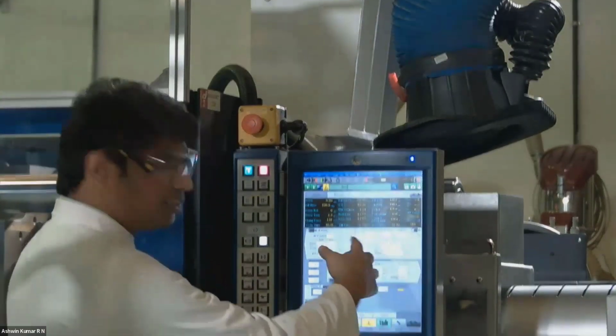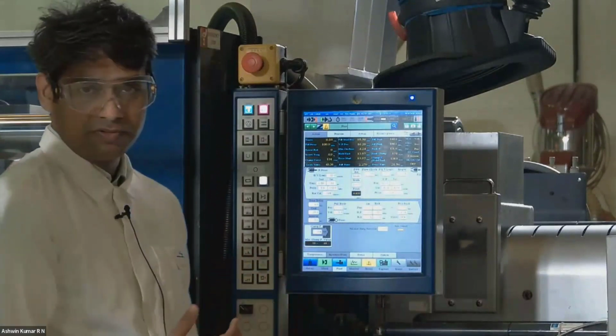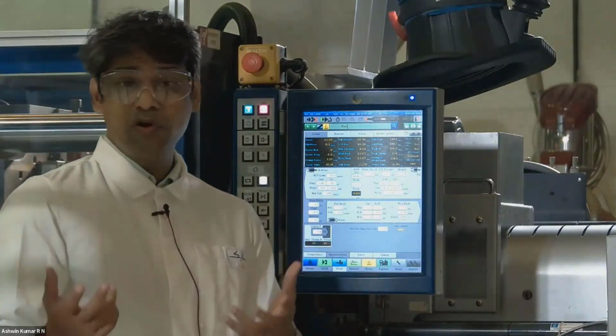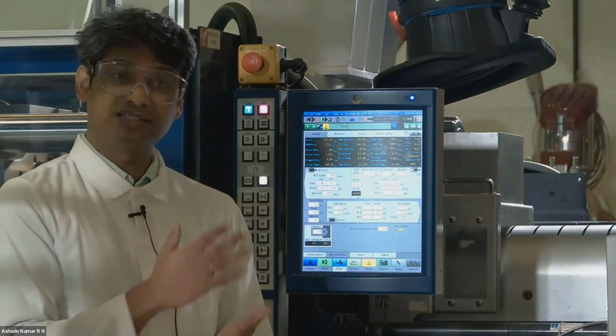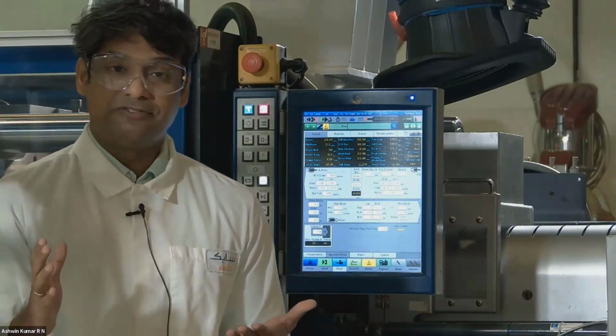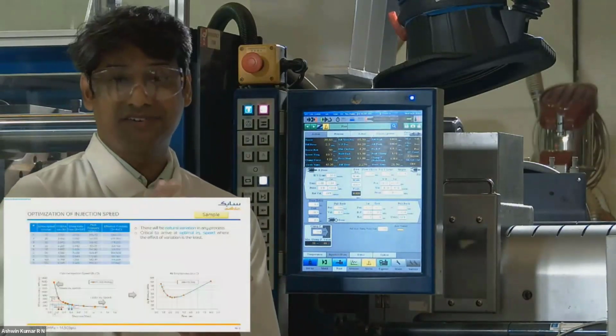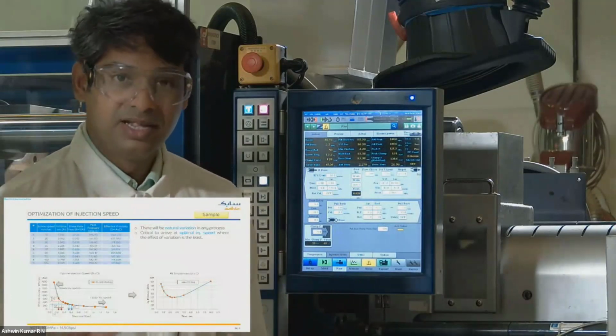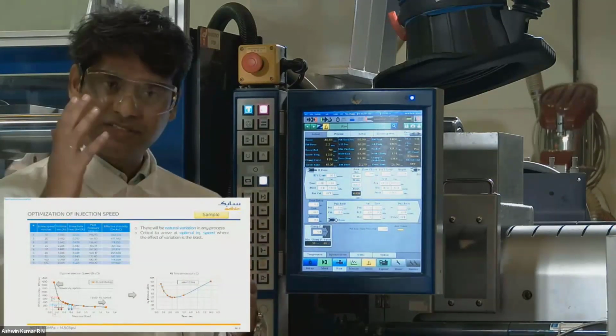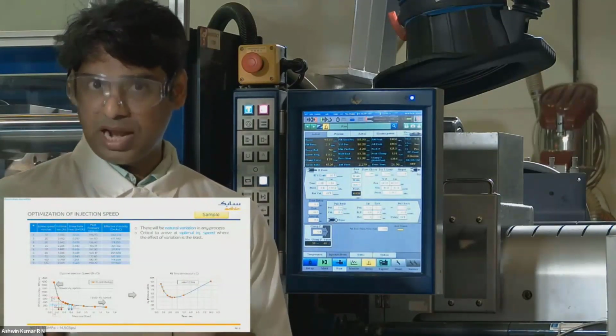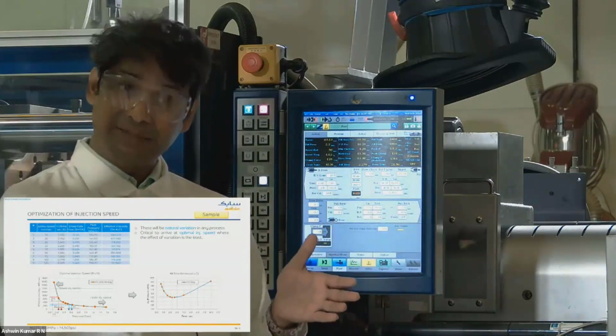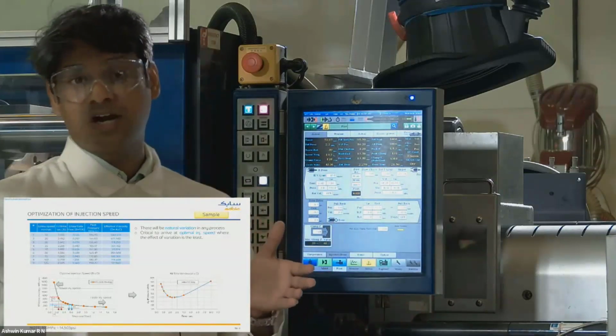And to highlight the filling part of it, we have employed the in-mold rheology to understand what is the optimum fill time, or the fill rate with which we want to fill the part. Now in this, we fix the screw start and the screw end position, and we keep changing the screw speed and monitor how the pressure is changing.